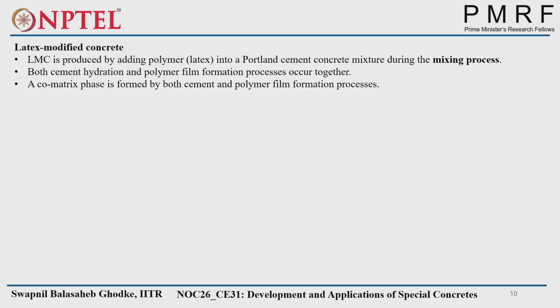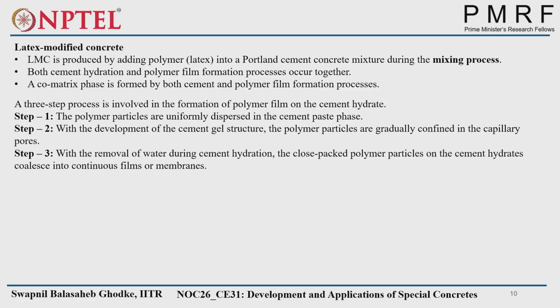Then third one is latex modified concrete. Here, in the case of the latex modified concrete, the polymer or latex will be added into the Portland cement concrete mixture during the mixing process. So here, hydration will also occur as well as polymerization process will also occur. So both cement hydration and polymer film formation process occur together, and that's the co-matrix phases formed by both cement and polymer film formation process. We'll see with the help of the image also how that process is carried out together.